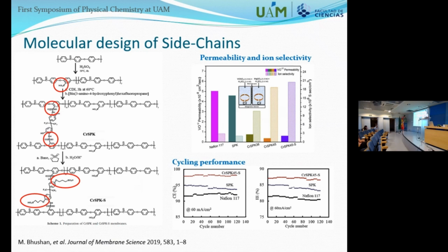Then they do the cycling performance. And again, this time it only goes up to 120 cycles. But okay, it's still quite a good experiment. And they get much better results than the Nafion membrane that they are comparing, and than the membrane without the cross-linking. So they can effectively see that this cross-linking strategy has been very effective to enhance the cycling performance of the membrane and the overall system.